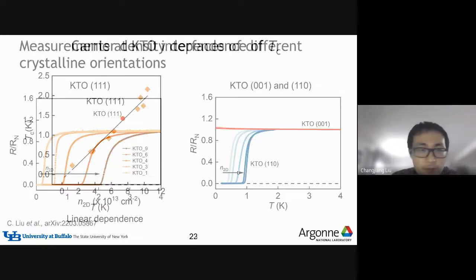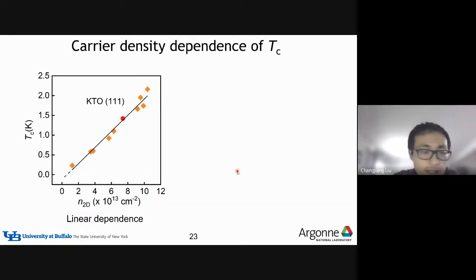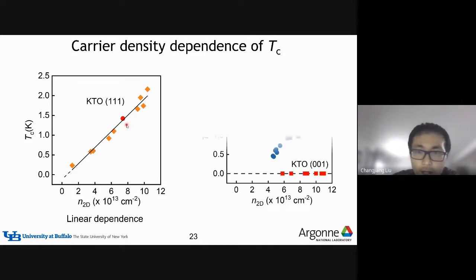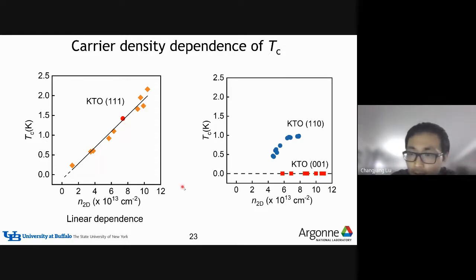You see that. So when we plot Tc versus n2D, we found that for the KTO 111 interface, it shows a linear dependence of Tc on n2D. While for other interfaces, for example KTO 001, there's no Tc, basically 0. For KTO 110, it shows an increase, but gradually saturates at a temperature of around 1 Kelvin. So you see that depending on the crystalline orientation, the superconductivity is quite different in terms of Tc. As I mentioned earlier, this should give us a strong clue about the origin of the superconductivity.